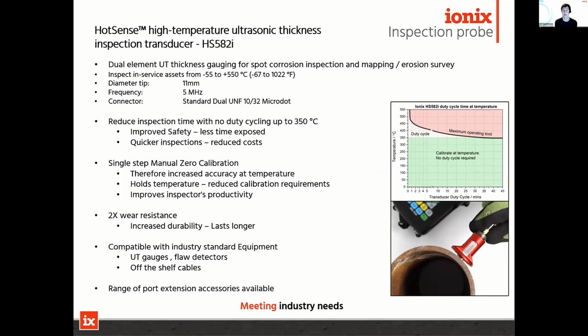The difference between this probe and ones that you might be using already is that it can be used continuously on surface temperatures up to 350 degrees C. And above 350 degrees C, up to about 550, you can use this probe, but with duty cycling. So the advantage of this high temperature is that it allows you to reduce the time at asset, because up to 350 C you don't need to duty cycle the probe, so your inspections are quicker. That also makes it safer.